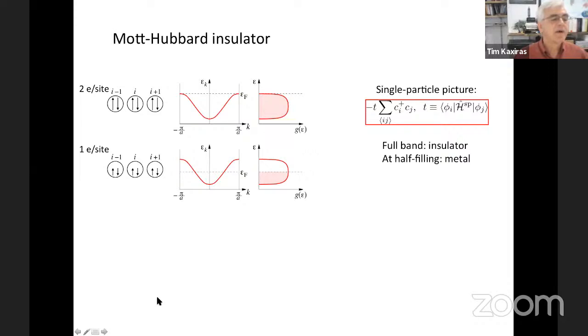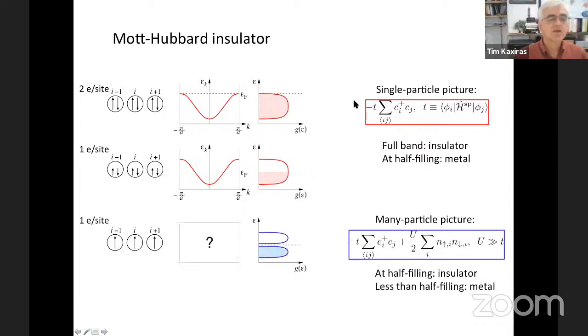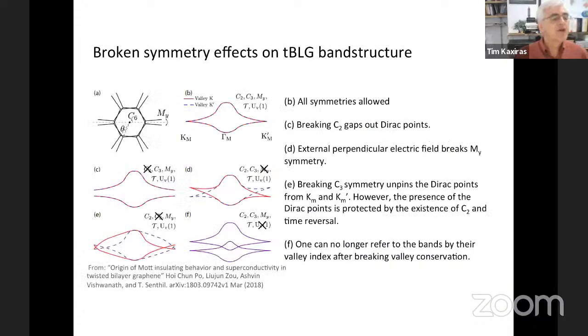So as I said earlier, the single particle picture cannot account for the Mott gaps. This is a very simple schematic, a single band, full filling, a single band at half filling. There's no band gap. Instead, you need a more elaborate model. So this could be a single particle model, which includes only hopping between sites. So in addition to hopping between sites, you need on-site repulsion or more elaborate models. So this is a many particle picture, which can produce this kind of splitting of the bands due to correlated electron behavior, and then you can have a half-filled band. And this is exactly the kind of level of description of the system that the previous talk was talking about. The question is, how can we build a picture using the single particle information of a many-body description?